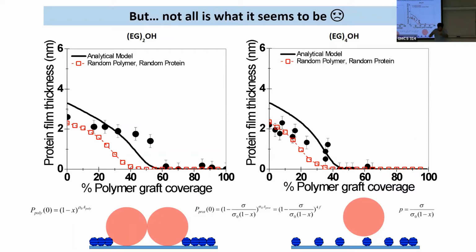If I take it back up and drop it on the same spot, now in my analytical solution, I don't have any memory that there was a protein here. So I drop it on the same spot and now there is nothing blocking it, and so now I can stick, right? Because it's a sort of sequential process. And so that's what helped me overestimate some of these curves.